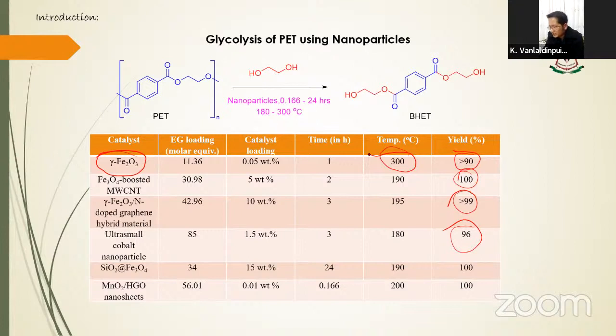And this is iron oxide boosted multi-walled carbon nanotubes. So using that one at 190 degrees Celsius, PET monomer was obtained in 100% yield. Very good yield. But one limitation, the limiting factor, is that the preparation of these nanoparticles is very problematic. Sometimes multiple steps have to be employed, and sometimes you have to use harmful chemicals for the preparation. So every catalyst, every procedure has some limitation.